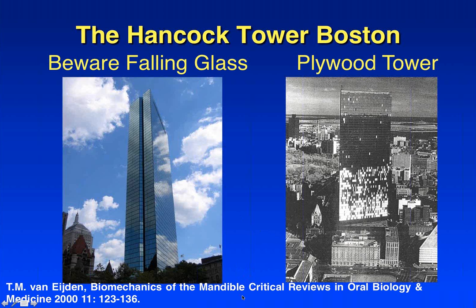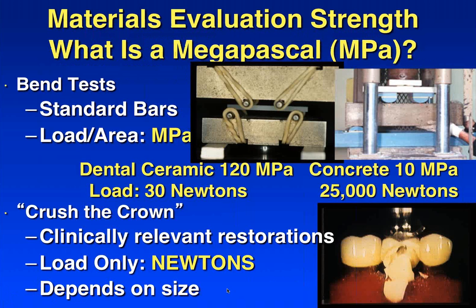And if you start looking in the literature, you see that there are also lots of issues with the jaw flexing. So when you think of making multiple unit restorations, the jaw is always flexing, and this is actually a very interesting paper. It has some interesting discussions about, again, implant restorations and what types of materials should be used on top of implants, or when we're joining multiple implants together with stiff materials like a zirconia may be a problem. So exactly what is the difference between strength and load-bearing capacity, which is what we really are concerned about when we're making restorations in the mouth.